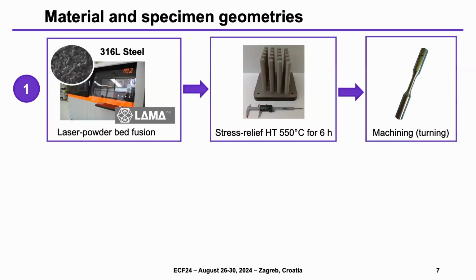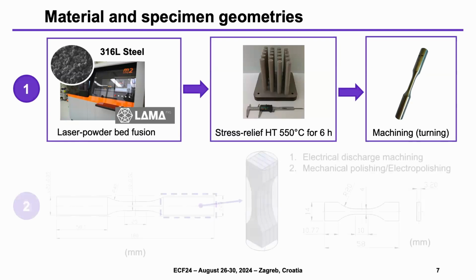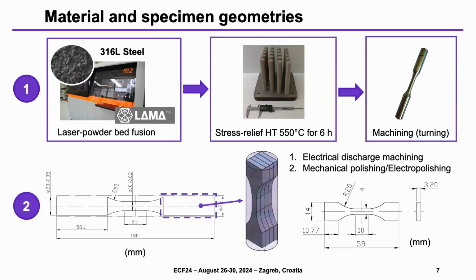Concerning the material, we fabricated some cylinders in the vertical direction using, as I said, laser powder bed fusion and the 316L steel. Then these cylinders underwent a stress relief heat treatment, and then they were machined to the specimen geometry. In addition to the cylindrical specimens, we also fabricated some flat specimens using EDM from the head grip of the cylindrical ones, and the surface of these flat specimens was also electropolished. These specimens were used to investigate the persistent slip marks during cyclic loading.